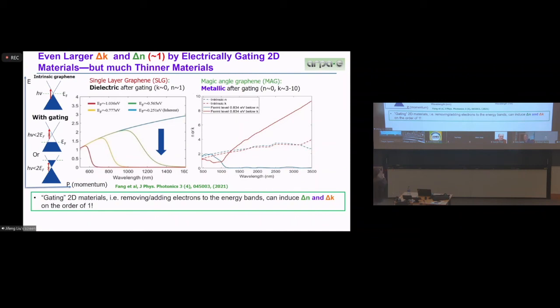Okay, so now if you do what we call electrical gating, that basically means you put two layers of graphene in a parallel capacitor configuration, you remove a few electrons from this hotel and move them to this hotel over here, the other side. You see that the photon can still promote you by 10 floors, but they find no guests in this hotel anymore. So the photon is transparent. And here, in the other hotel, you already filled the 20th floor. So even though you have a coupon for promotion, you have nowhere to go. So after you do the gating, the graphene becomes from opaque to transparent.